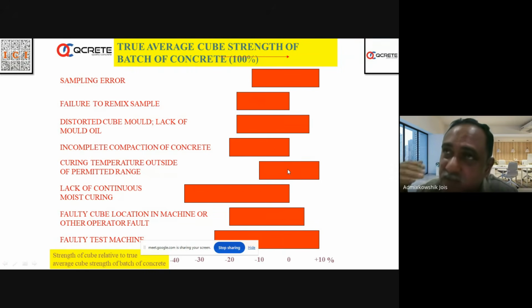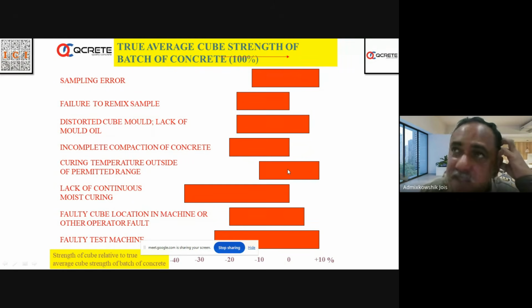So it will meet the requirements if it is cured at proper temperature, and the curing should not be intermittent. Curing should be continuous. So if there are columns on site, and somebody pours water in the morning, comes back in the afternoon, again pours some water and goes, intermittent curing is more dangerous than continuous curing. So we have to have a proper curing regime. Many times in big projects, today columns are cast in the morning, and they de-shutter tomorrow by, say, 11 or 12 o'clock when the temperatures are high. And then after de-shuttering, it is not attended to because many columns have to be de-shuttered. So they start curing after 1 day or 2 days. So you will get lower strength.